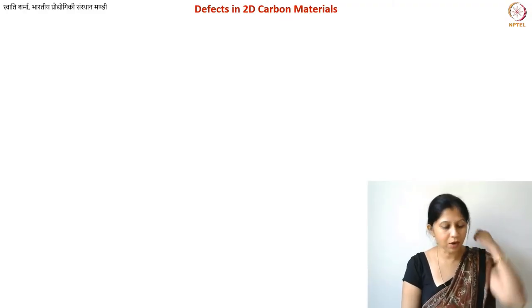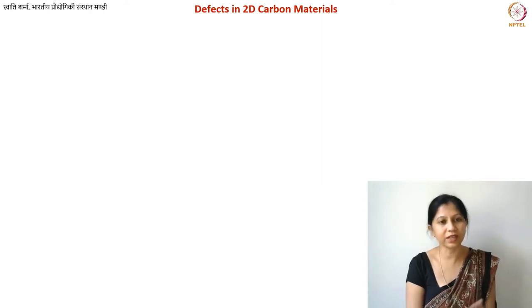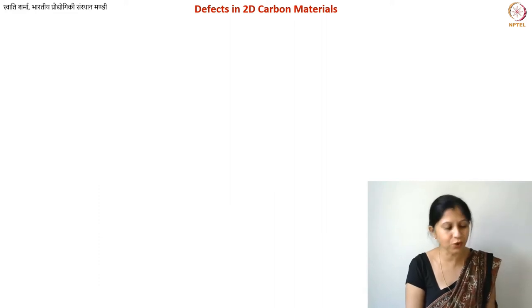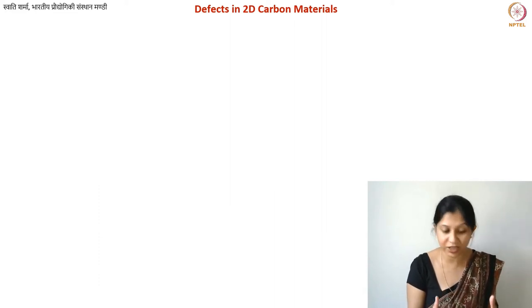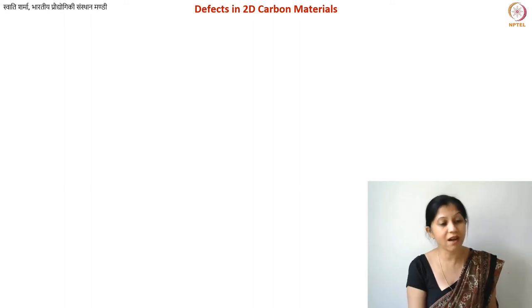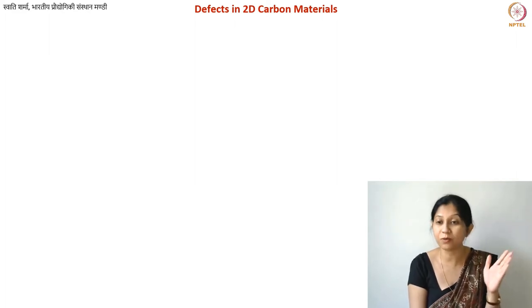Let us talk about what are the possible defects in two-dimensional carbon structures. I'm not saying defects in graphene because graphene by definition is a defect-free single layer of carbon. So let's say defects in two-dimensional carbon. We do know that when these graphene-like sheets are present in bulk carbon materials, especially non-graphitizing carbons, there is a significant number of non-six-membered rings, which is responsible for the curvature.